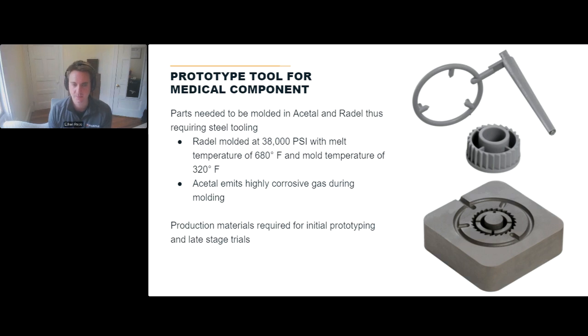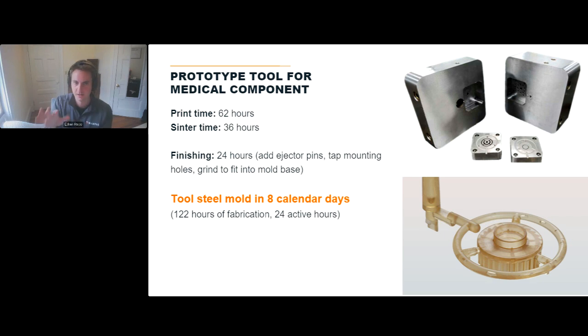Again, this was a prototyping here, and they were doing some late stage trials, so they needed to be molding these parts inside of a steel tool rather than an aluminum tool. So it was really important for it to be in an H13 tool. Printed these 2 inserts you're seeing here in 62 hours, so about 2.5 days, in the furnace for a day and a half. They did 24 hours of finishing, just adding the ejector pins, tapping the mounting holes, and grinding it to fit into the mold base that you're seeing above. They didn't do any finishing to the actual feature detail, and they got that sort of matte EDM style finish that you're seeing on the part here.